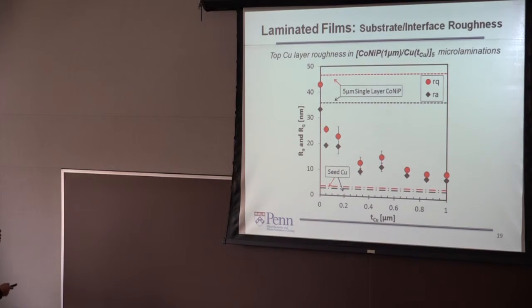So what we do here is we have a 5-pair cobalt nickel phosphorus, 1 micron, and various copper thickness. And we measure the top copper layer roughness using AFM. And this is some representative scans shown over here with the increasing copper interlayer thickness. And for your reference, the seed layer copper is shown over here, and the single layer 1 micron cobalt nickel phosphorus is shown over here. As you can see, when you increase the interlayer thickness, intuitively it smooths out the surface. The detailed roughness data is shown over here. So RA is the arithmetic mean, and RQ is the root mean square.